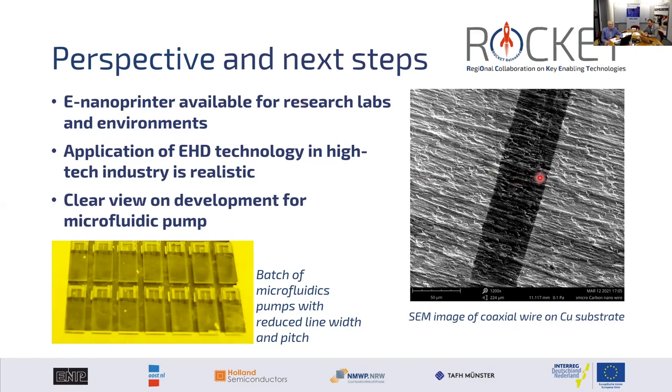With this direct write nanoprinting, we try to break through this barrier and move into the range of 1 to 10 micron or even below 1 micron, depending on applications. So instead of pushing a droplet out of a nozzle, we pull the droplet and create a jet, which is of sub-micron or micron dimension. Yes, and as you already mentioned, the faster you go, the thinner your print lines will be. So it's getting even smaller and thinner.